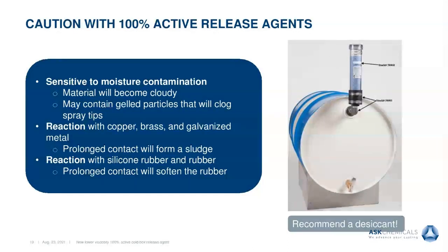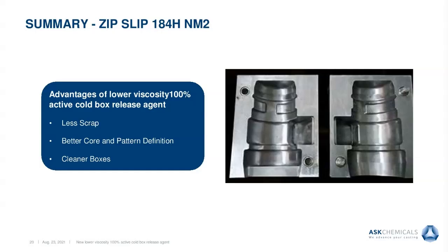Newer formulations such as 184H and NM2 are less sensitive than prior versions, but still may be affected. It is recommended that a desiccant be added. Drierite sells these. And the picture on the right shows a drum with a Drierite desiccant added to it. Using a lower viscosity 100% active cold box release agent has many advantages, including less scrap, better core and pattern definition, and cleaner boxes.